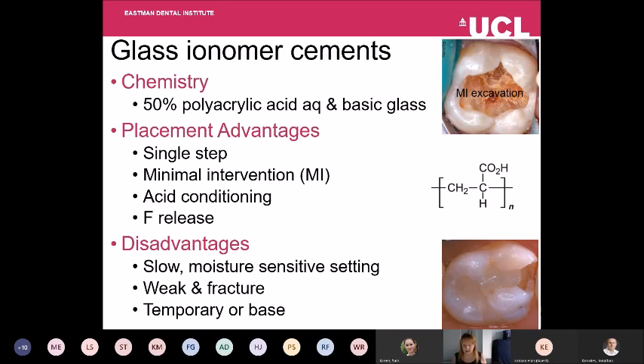The major advantages: you can place material in a single step, you can use a minimal excavation method, only taking out the top surface tooth structure. You usually don't need to condition the tooth. Instead of with phosphoric acid, you use a solution of the polyacrylic acid. The benefit as well is that you can get release of fluoride. What the fluoride can do is help to get the tooth underneath the restoration to remineralize.